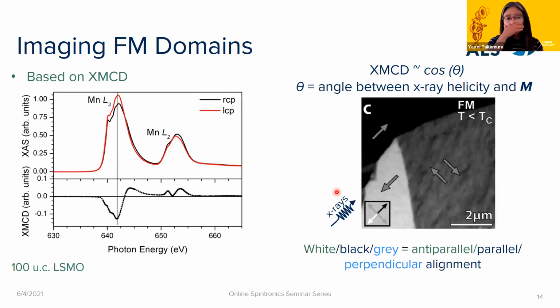Okay, and so what you'll see in terms of images is shown here. Again, this is that same manganese XAS and XMCD spectra that I showed you before. What we'll do in a PEEM experiment is tune to this energy here, just above 640 eV, where we have a maximum dichroism. So the magnetization is the strongest at this particular energy. Then we'll take images using both right and left circularly polarized light, and then we'll do a dichroism: a difference divided by the total intensity. That will give us these images here. We do that mathematical operation in order to remove any topographical or work function differences from the different locations in the images, so that we get just the magnetic information.